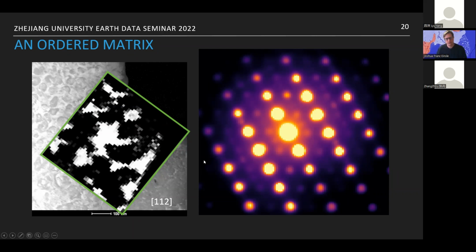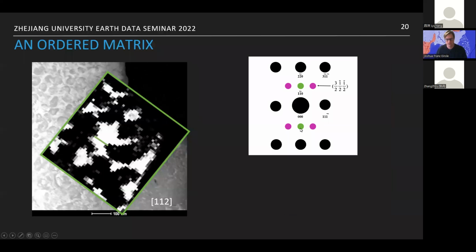This is where I really like to point out that machine learning took us a long way down the right pathway in analyzing this sample. However, at the end of the day, it produced a result that was hard to interpret, and we didn't understand what was happening. So we ended up looking at the raw data again, because, like I said, we have these forbidden reflections. We just scan back and forth across this one single point in the data. We're not actually running a physical experiment, we're just looking at the raw data. By scanning across this linear region of the matrix, watch what happens to those reflections.